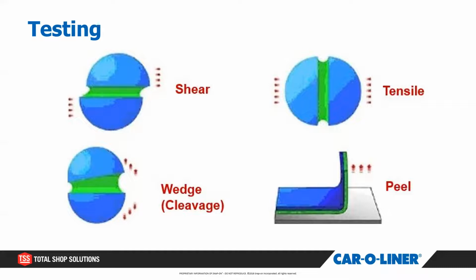And again, when we look at this, I like to use resistance spot welding as an example. When you're doing a destructive weld test on a resistance spot weld, you're going to take the vice grips and basically peel it. You're trying to peel it apart. On the weld, actually, you're trying to pull the nugget out and make sure that it's done properly. That's exactly what this test is doing. It's just peeling it apart. It's measuring how much pressure it takes to peel the joint apart.